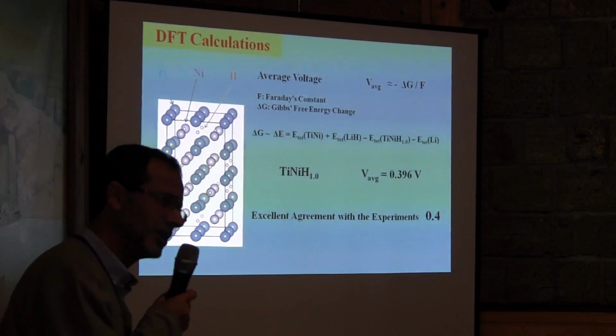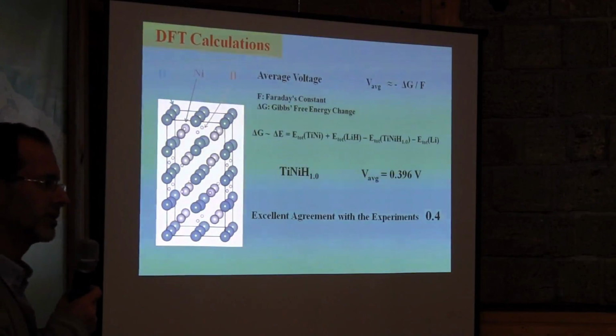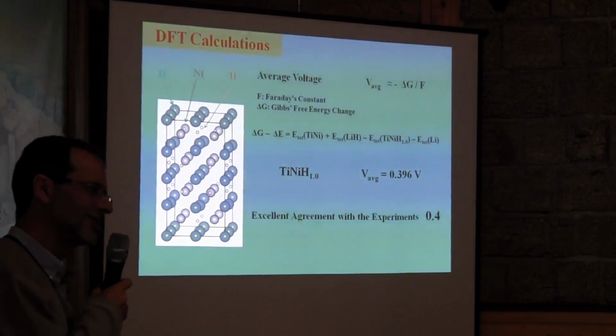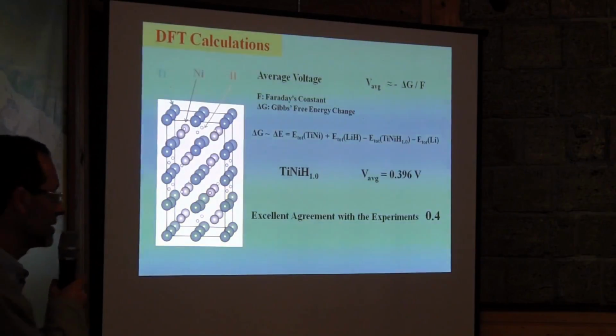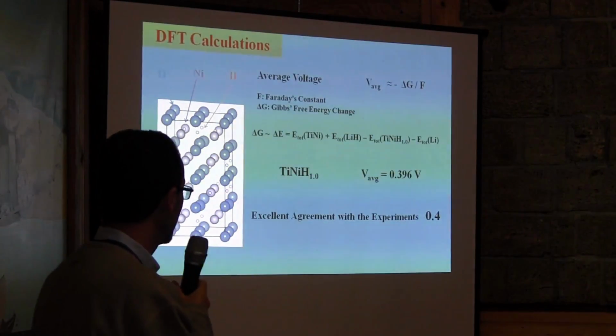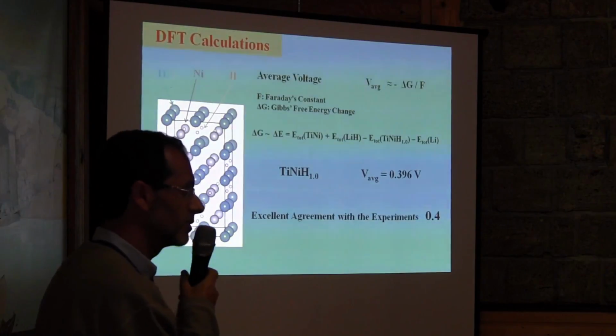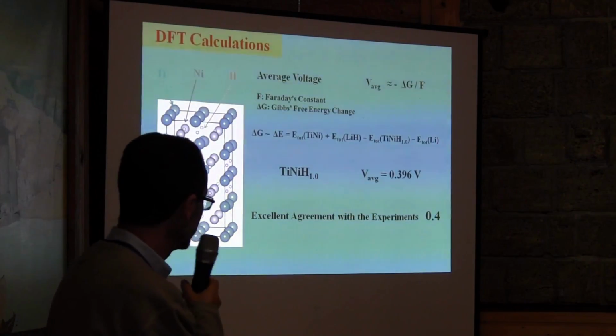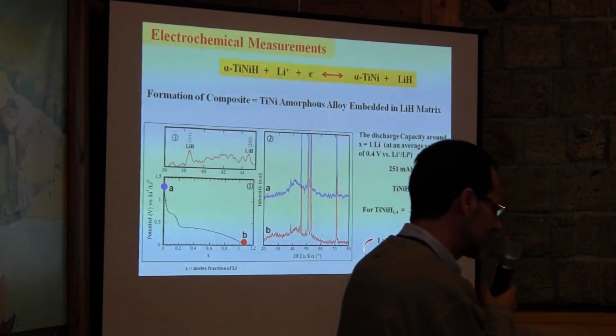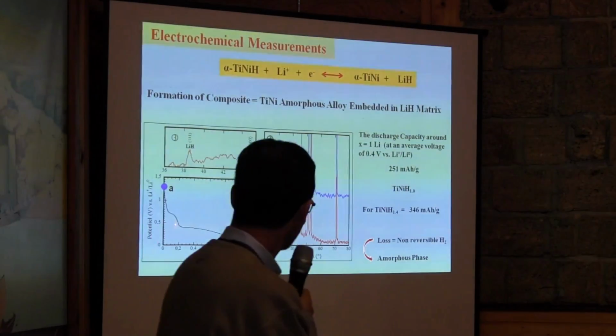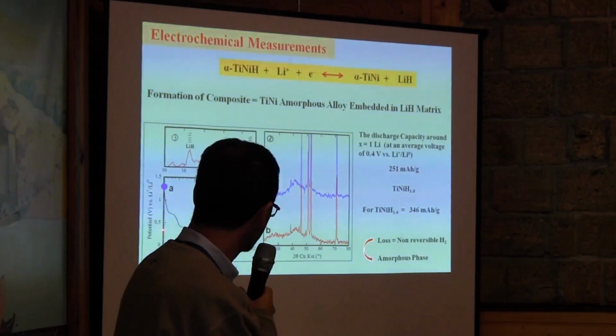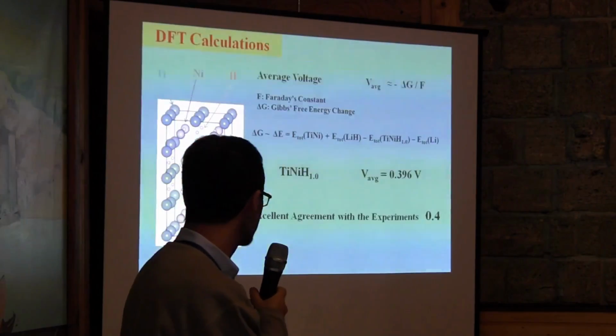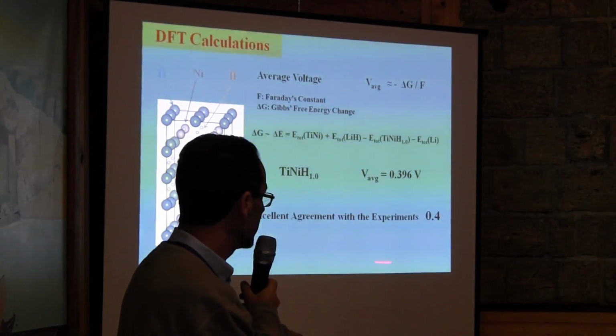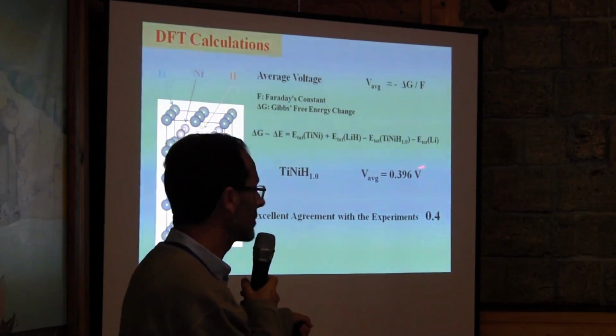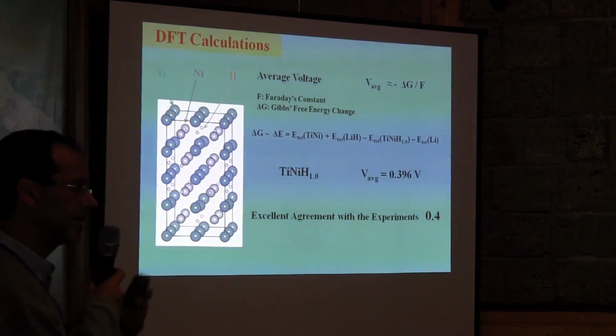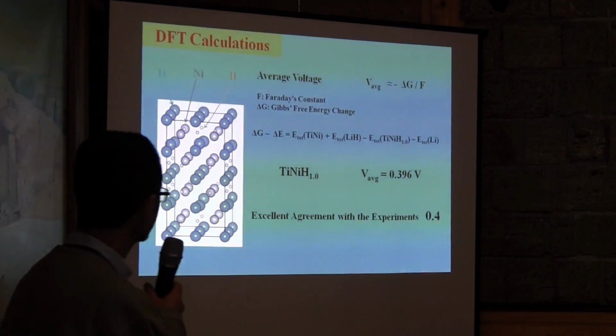So now we did DFT calculation again, because it's a support for our results. If you want to publish in good journals, you need to add some modeling. So we did DFT calculations, and we obtained very good correlation between our results. So if we come back to the previous slide, you can see the plateau of reaction is around 0.4. And from DFT calculation we find the same plateau. So we can predict with our calculation.